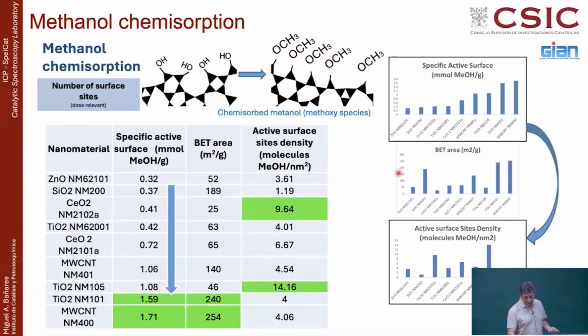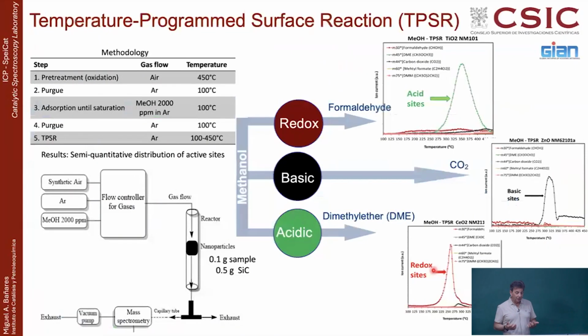Some materials have very high area, others have very low area. But actually, materials with very high area, like these two, they don't have so many sites per square nanometer. So they have a big area, but this area is not that crowded with active sites. And other materials with low area have a lot of active sites in these few square meters. So maybe you have less area, but very crowded, very active. And others have big area, but less active. And that explains why they found that silica typically has a lot of area, but it's not very reactive. And they didn't know why. But then they said, okay, fine, there is a lower number of sites.